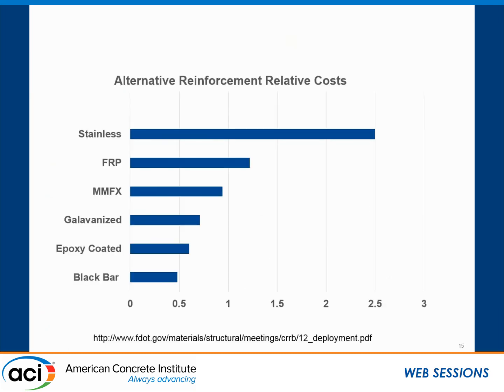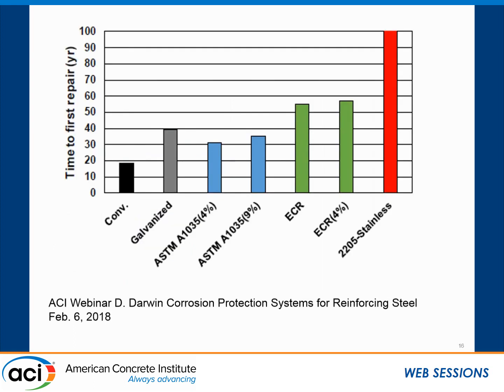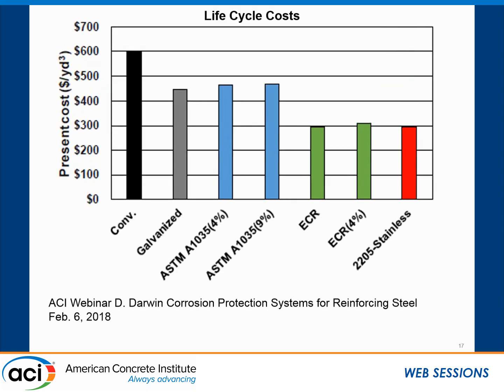Here's one estimate of cost difference, upfront cost. Look at how much more stainless costs, 2.5 times more than black bars. But if you look at the time it takes to repair, stainless is over 100 years. Conventional reinforcing, 20 years. And everything in between. Or if you look at the life cycle costs, conventional steel has the highest life cycle cost. And stainless, one of the lowest. Epoxy-coated reinforcing in this study also worked very well.